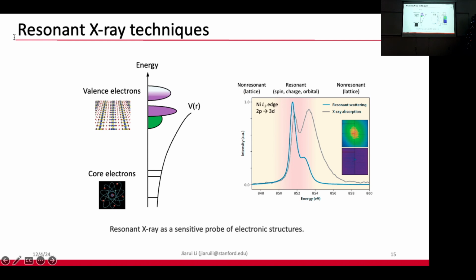And the technique that we use to enhance this sensitivity towards the valence electrons is called resonant X-ray techniques. It is a technique where we can tune the X-ray photon energy to match the energy level difference between the core electrons and the valence electrons. And one example is shown on the right, where we can first look at the black curve here. This is the absorption, where we can control the X-ray photon energy across one of these atomic transition edges called the nickel L3 edge, which is the transition from the nickel 2p level to the 3d level.